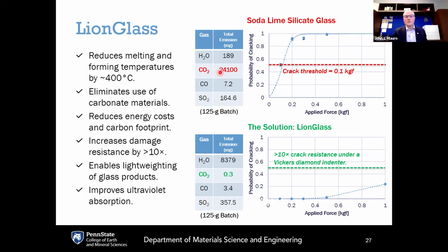And you get 24.1 grams of CO2 that gets released. And the lower table here is for the same size batch for Lion Glass. All the carbonates are eliminated, and so the total amount of measured CO2 was 0.3 milligrams. So it's like atmospheric CO2, basically. So that contribution to the carbon footprint is eliminated. The contribution from energy consumption is greatly reduced because of the significantly lower melting temperatures by about 400 degrees C.